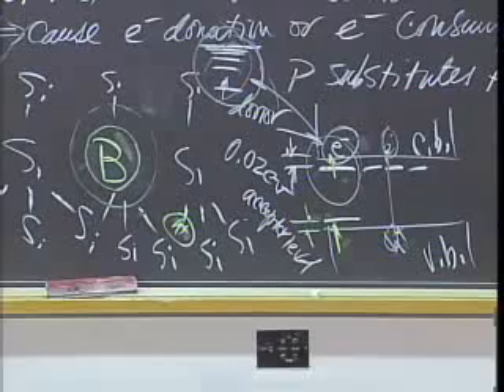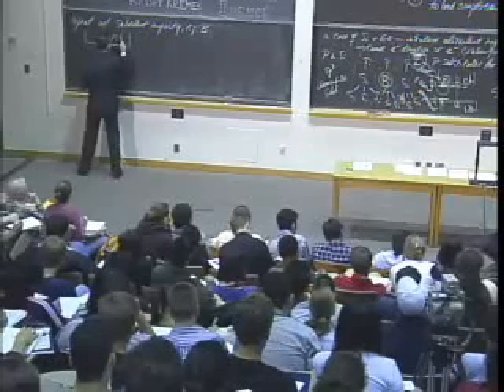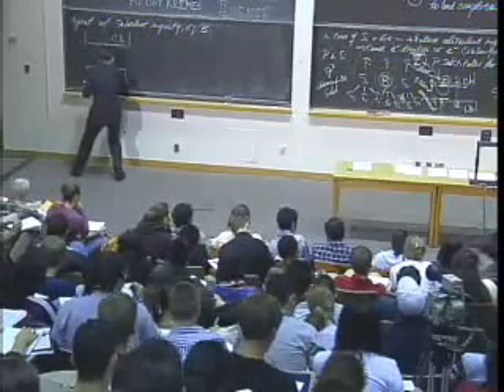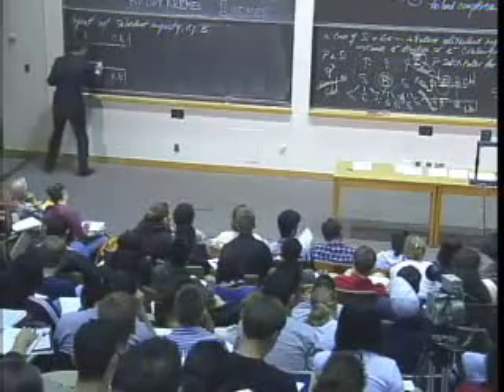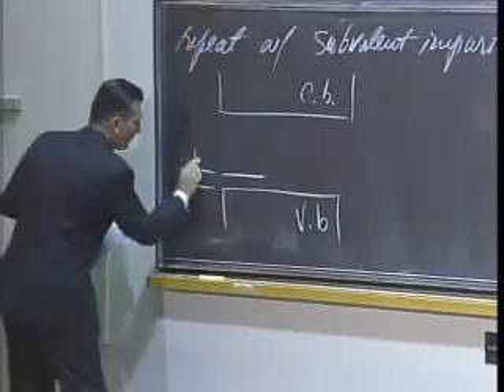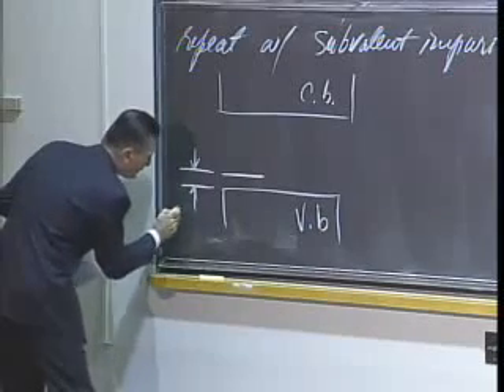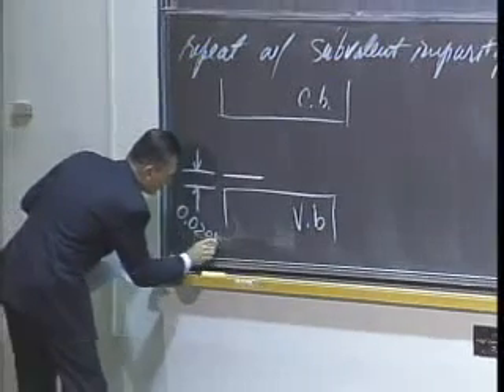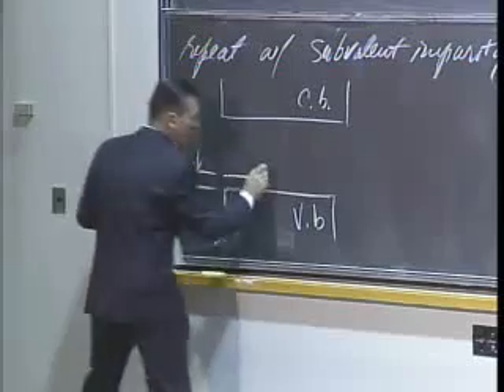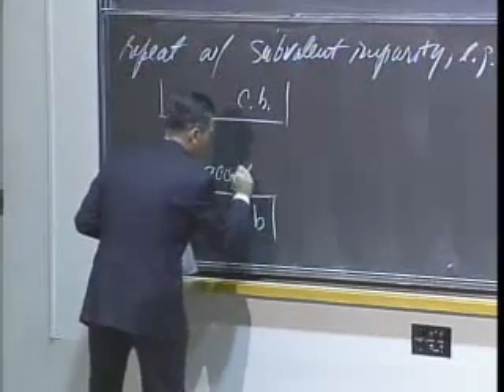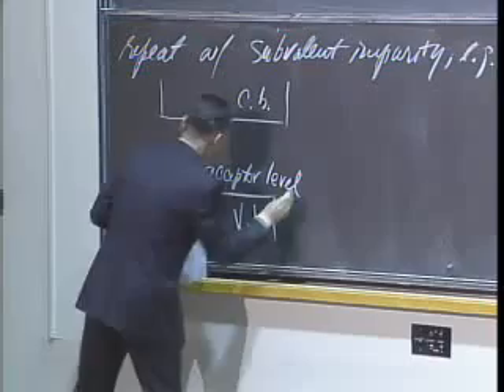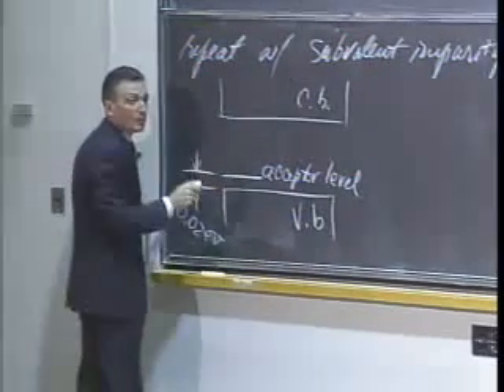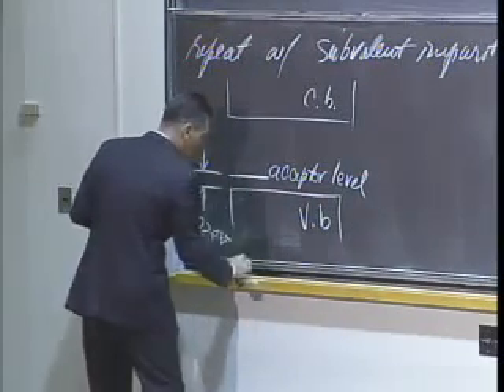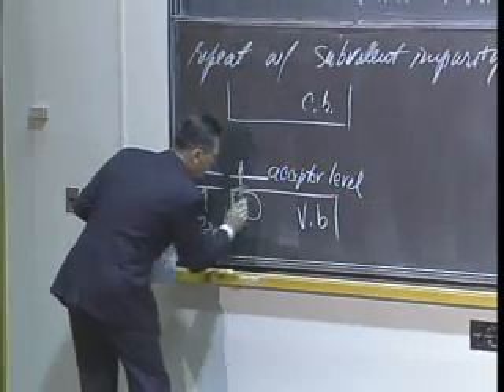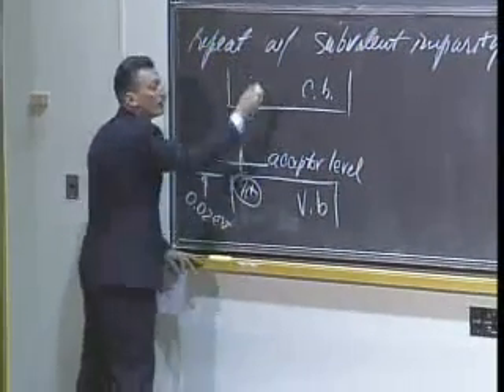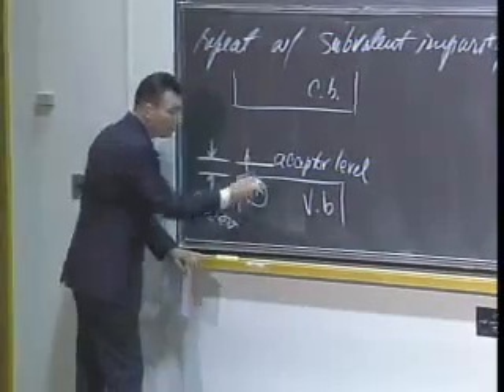So now we have this configuration. Conduction band, valence band, subvalent impurity. This is not to scale, of course. This is on the order of 0.02 eV. Okay? And this is called the acceptor level. We get thermal excitation, leaving holes behind. So thermal excitation promotes the electrons up to here and leaves behind holes. So every time I put in a subvalent impurity, the result is a hole.